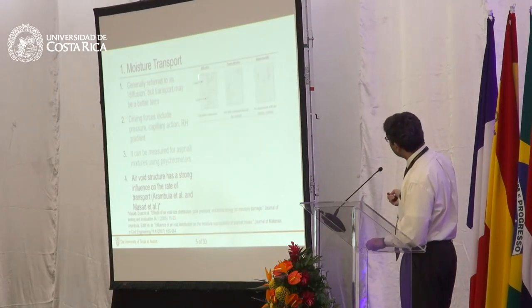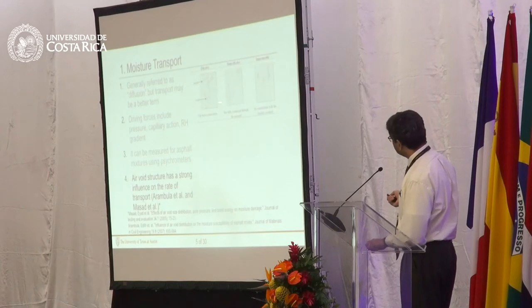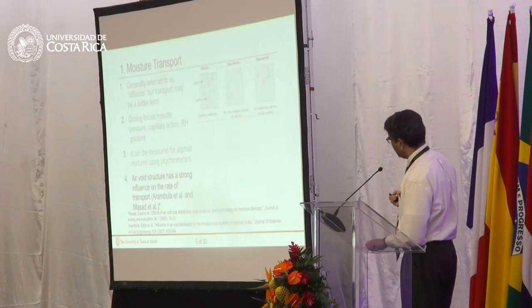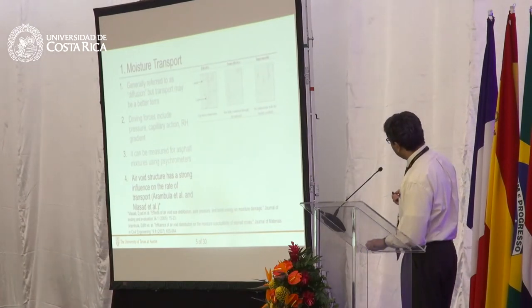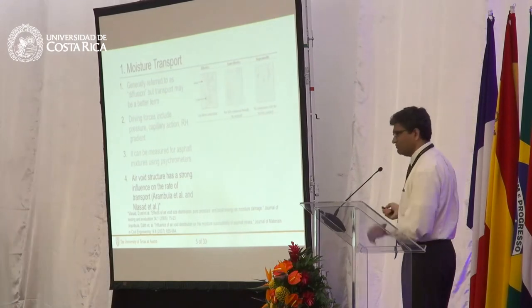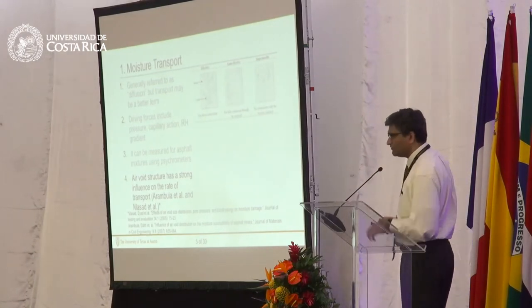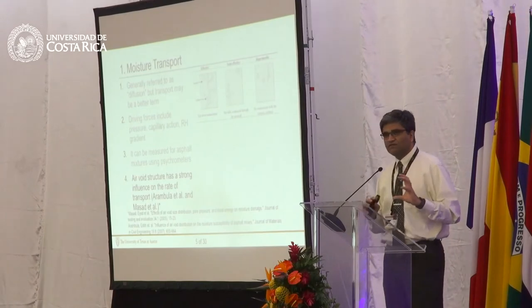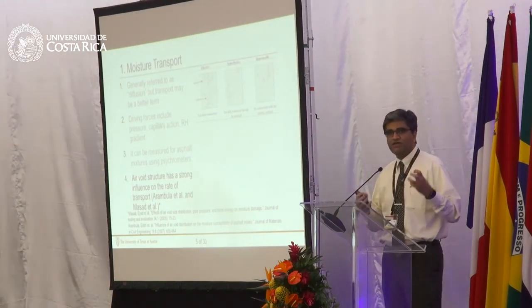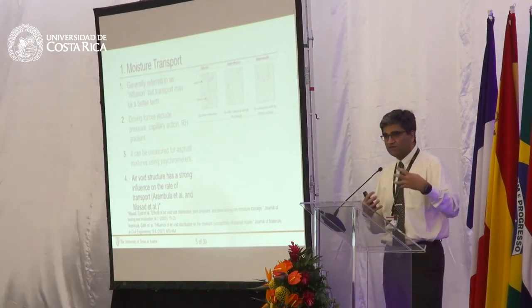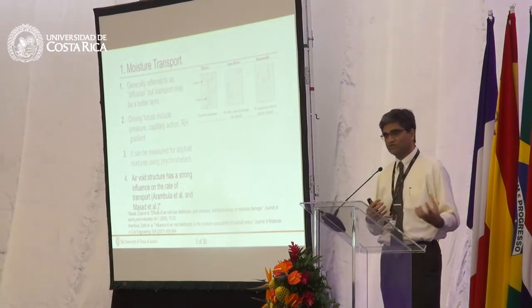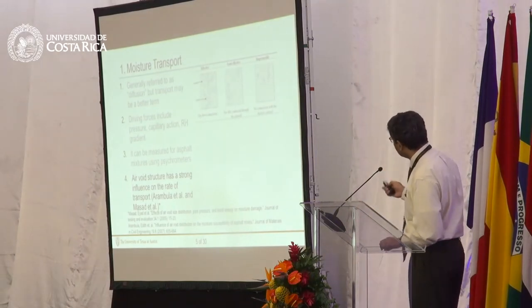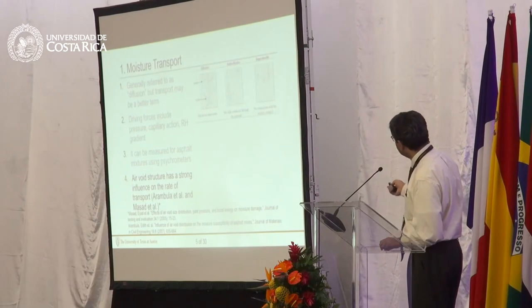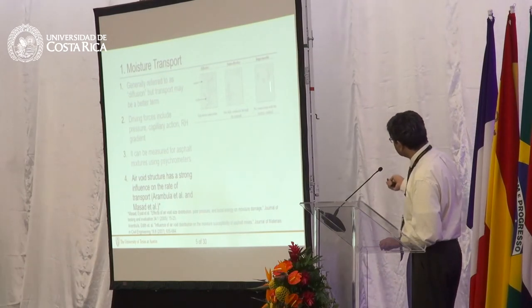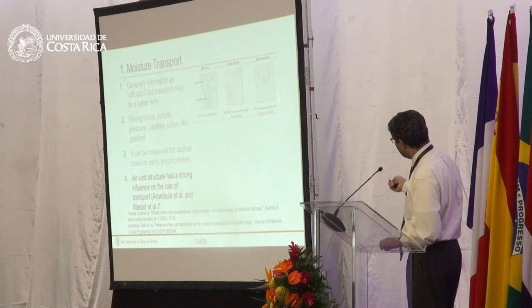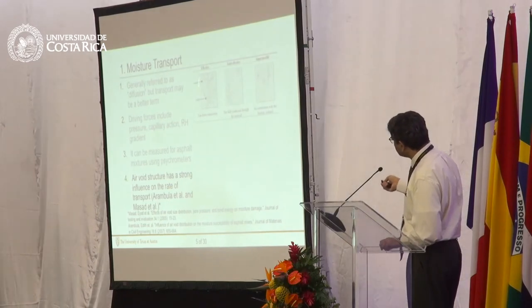You can see that you have one scenario here which says very effective or open air voids, and then you have semi-effective air voids, and then you have an impermeable scenario, meaning you can have air voids that exist in the mixture, but they are not permeable, meaning water cannot get into or out of those air voids. And that's okay, because you've created a scenario where this whole thing is tight and does not allow water in or out. This extreme scenario is okay too.